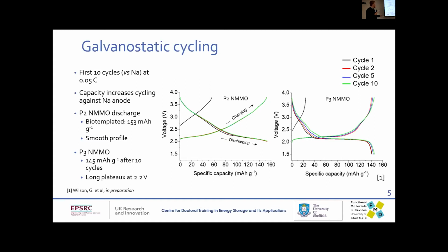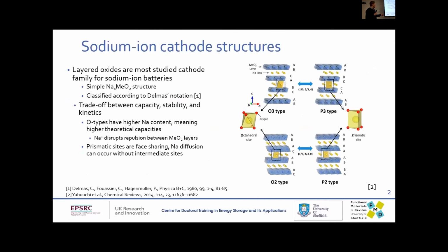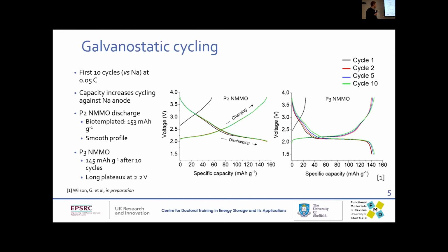Key thing to note, this P2 has a reasonably smooth voltage profile. It's not completely smooth, it's not a straight line, but it is reasonably smooth, which seems to indicate that there's not really a significant phase change going on. Compare that to the P3, which has this very long plateau, about 2.2 volts, and it's very likely to be a phase transition. What I think is happening, and I need to confirm this with some operando XRD, is that as it's discharging, so you're putting sodium in, it's converting to this O3 phase in situ, and then converting back as you charge it. So that's how they perform separately, pretty good.